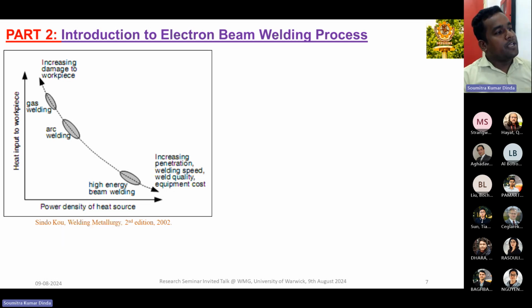Power density is very high. In the case of heat input, the unit is near 10 to 100 watt, but in the case of power density it is 10 to the power 5 to 10 to the power 7 watt per millimeter square, because the beam diameter is very small, in microns. So this high energy beam density gives very good penetration, very high welding speed we can achieve, and quality weld we can get. But if the heat input is quite high, then it will damage our workpiece over a much larger area.